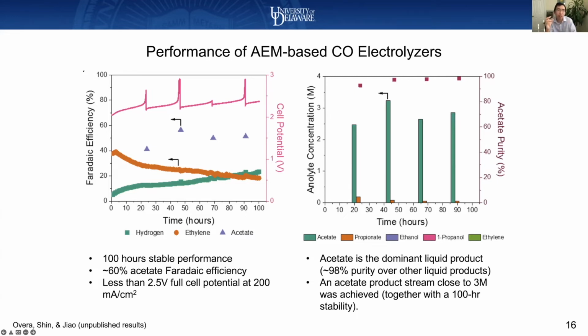For this particular cell configuration, I also want to mention that what we achieved is about 60% acetate Faradaic efficiency. This is the highest that has ever been reported in the literature. Actually, our results haven't been published yet. And the rest of the Faradaic efficiency goes mainly into ethylene and hydrogen as the byproducts.